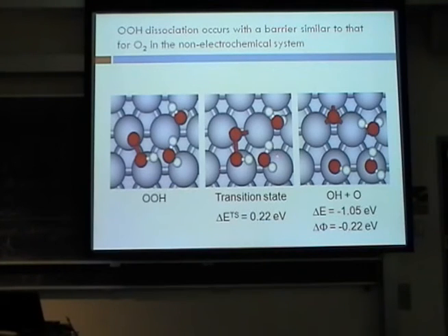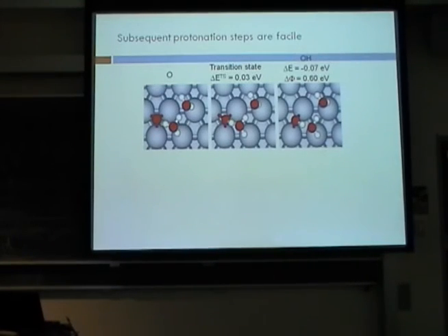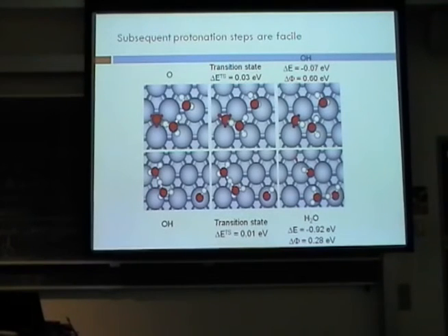And then we can probe the dissociation, for example. We see that the peroxy dissociation is the next energetically preferred step, and that on flat terrace sites, actually, you don't form much hydrogen peroxide, and that's mainly on the defects. The subsequent steps are maybe a little bit easier to understand. I won't talk about those. You just get proton transfer to O, and then proton transfer to OH to ultimately make a water molecule. And then if you were doing water oxidation, so water splitting to make hydrogen and oxygen, this would just all be in the reverse direction.